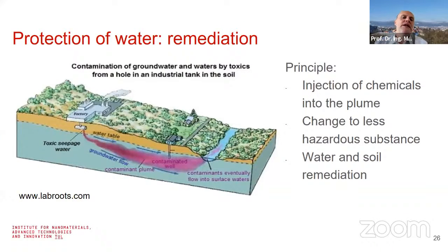So I would like to show you more pictures about remediation of contaminated soil, application of zero valent iron nanoparticles. The problem is that, of course, industrial production makes a lot of waste, and one of the wastes is seepage from the tank. In many cases we use, or mainly historically used, some chlorinated hydrocarbons like tetrachloroethylene and trichloroethylene in the industry, and these were stored in tanks which were not protected against leakage, and there was leakage from this tank, and it makes a contamination plume, which is in the red color on the picture.